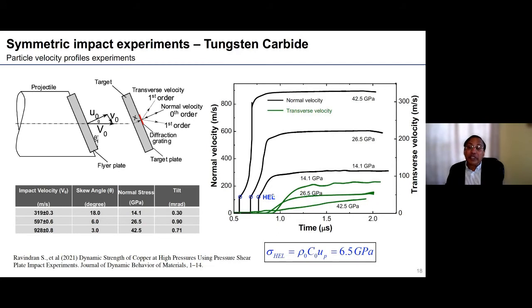And this is the normal velocity, as I mentioned, which ranges from about 300 to 900 meters per second. But the transverse velocity is much less. And here the obliquity angle, the skew angle, ranges from 18 degrees to 3 degrees. As you see here, we reduce the skew angle as we increase the pressure or the impact velocity to prevent sliding. And so we go as low as 3 degrees. And also we maintain very good tilt, less than 1 milliradian.